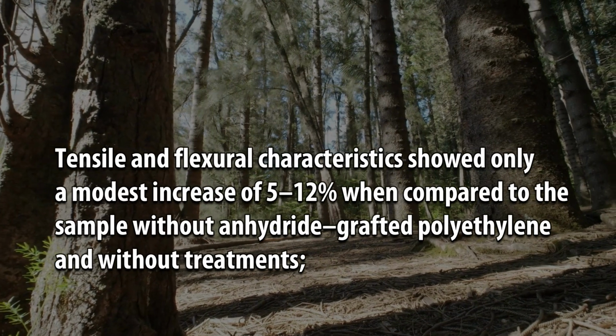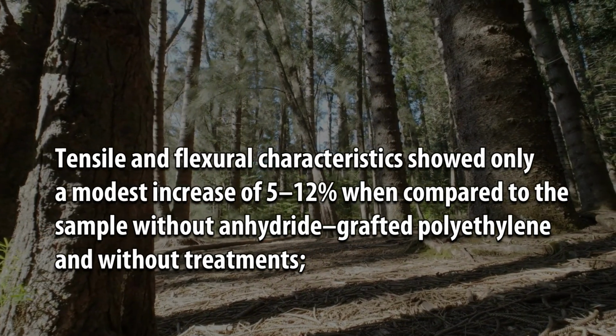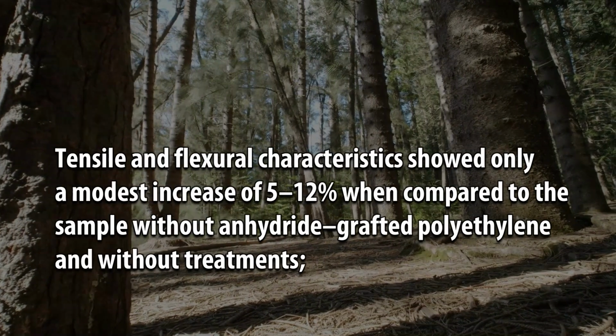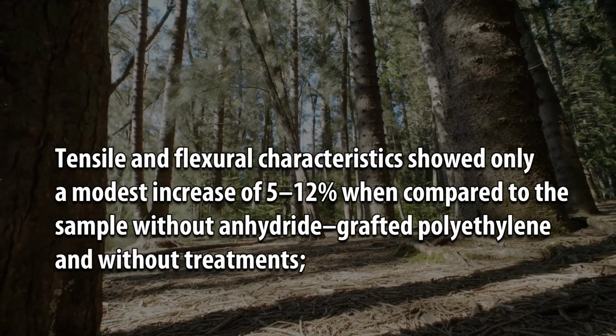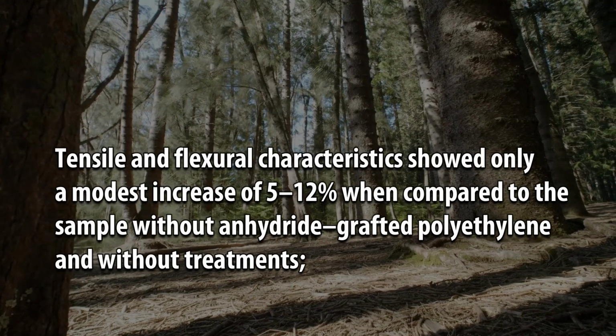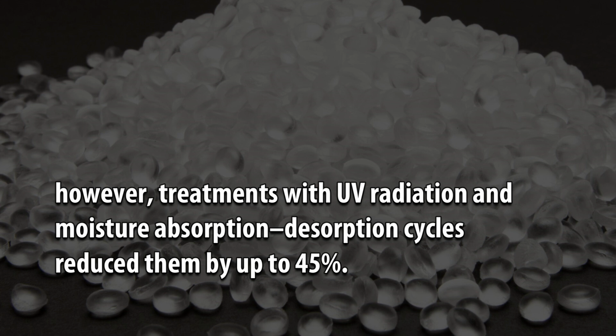Tensile and flexural characteristics showed only a modest increase of 5–12% when compared to the sample without anhydride grafted polyethylene and without treatments. However, treatments with UV radiation and moisture absorption-desorption cycles reduced them by up to 45%.